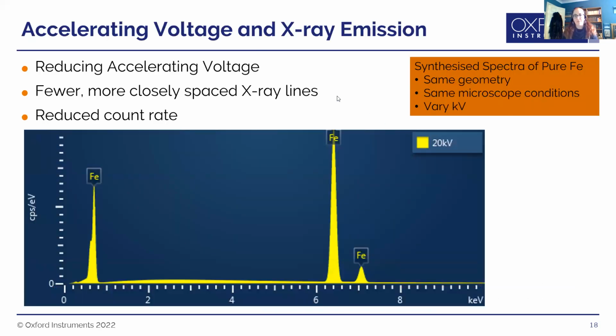But there are problems with just reducing the electron accelerating voltage. Here we've got a spectrum on an iron sample at 20 kV, and you can see really nice peaks, with the K lines here and the lighter lines here. But if we drop down to 15 kV, you can immediately see a reduction in the amount of X-rays.